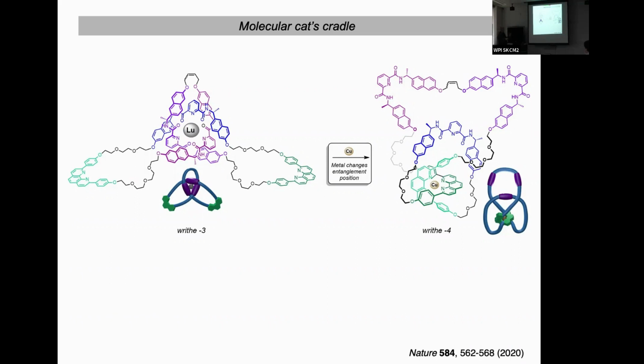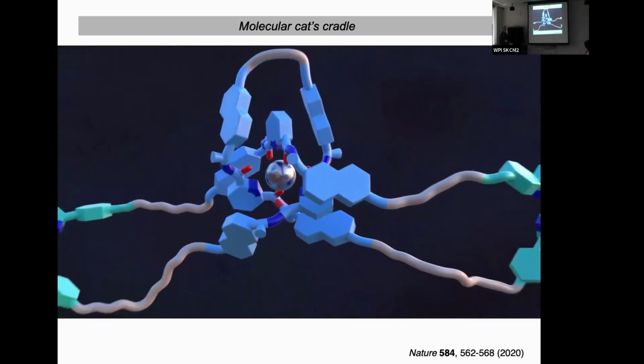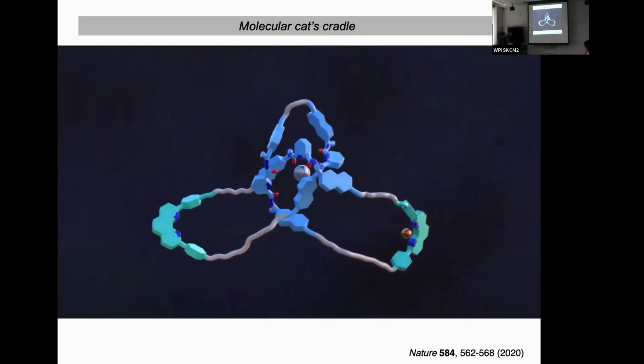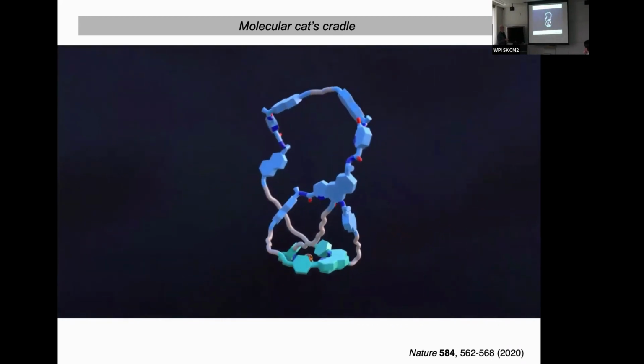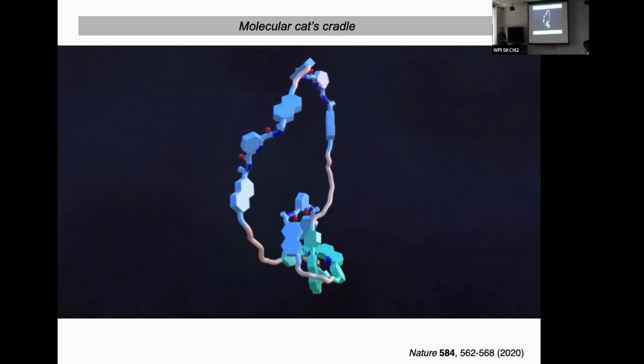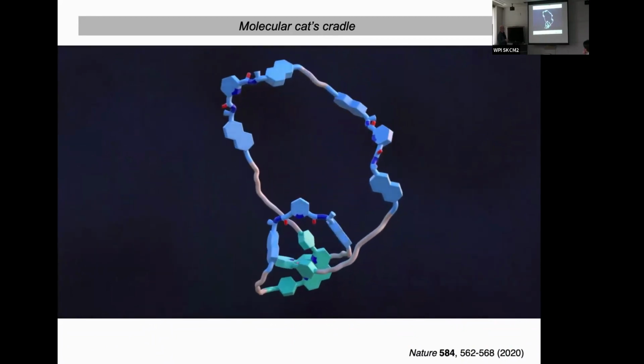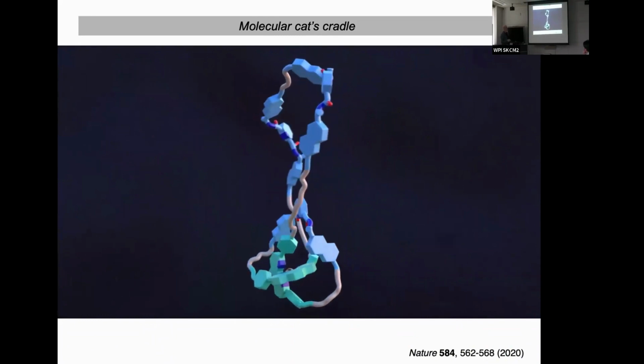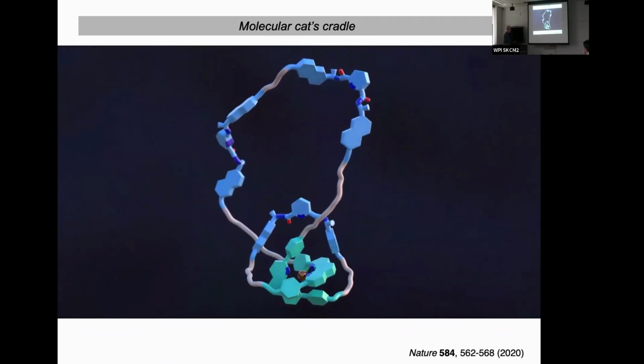In the trefoil knot, it can't bind both ions at the same time because of the conformational restrictions on the structures. So what had actually happened here was that the copper had displaced the lutetium to bind with the copper binding sites, and that leads to a different conformation of the knot. This has got a writhe of -4 instead of a writhe of -3, even though it's the same knot. It's got a different conformation. So this is like molecular cat's cradle, this game that children play where they twist loops into different structures. Here, the copper replaces the lutetium and ties it into this new conformation of the knot with a different rise and different strain in the actual knot just by changing the metal ion.